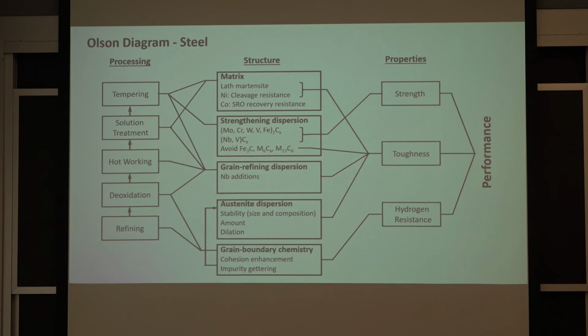Martensite is stronger than ferrite. Sometimes martensite is too brittle for an application, so you do what's called a tempering step, where you use precipitation hardening to increase the toughness of the material. Okay, so those are the processes that you might use in order to make a steel component.